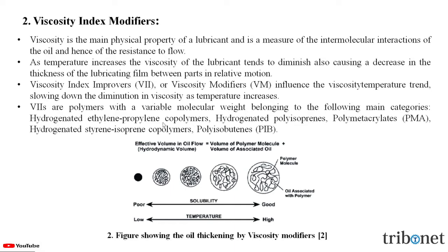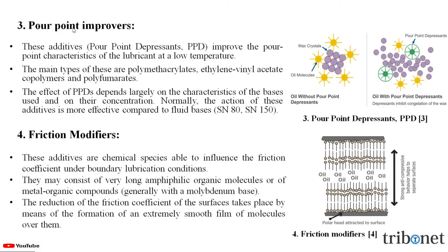Hydrogenated ethylene-propylene co-polymers, hydrogenated polyisoprenes, polymethacrylates (PMA), hydrogenated styrene-isoprene co-polymers, or polyisobutenes. In this figure, we can see how the viscosity modifiers increase the oil characteristics based on solubility and temperature.